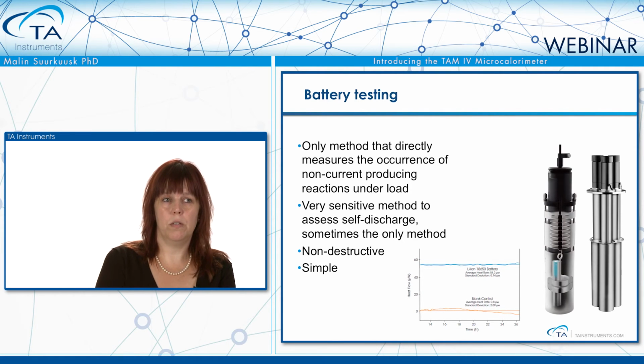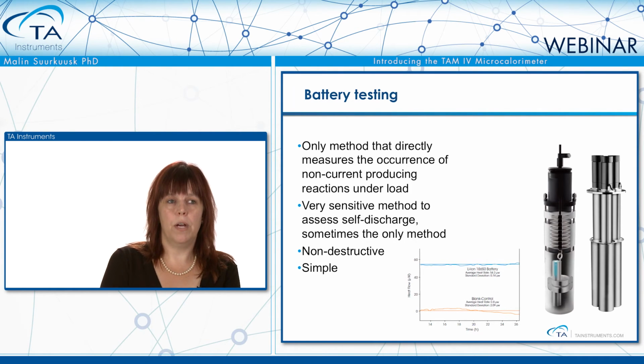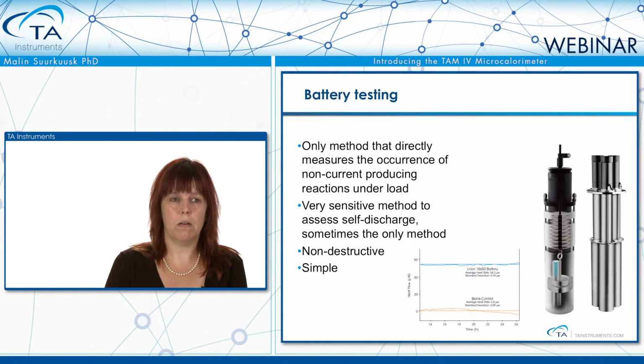Microcalorimetry is the only method that will directly measure the occurrence of any non-current producing reactions under load. It is also a very sensitive method to directly assess self-discharge. Sometimes it's the only method because it needs the high sensitivity. It is a non-destructive method, so the batteries could be further analyzed after the measurements, and it's simple. Put the battery inside the calorimeter and measure. The picture shows self-discharge of a lithium-ion battery inside the microcalorimeter.